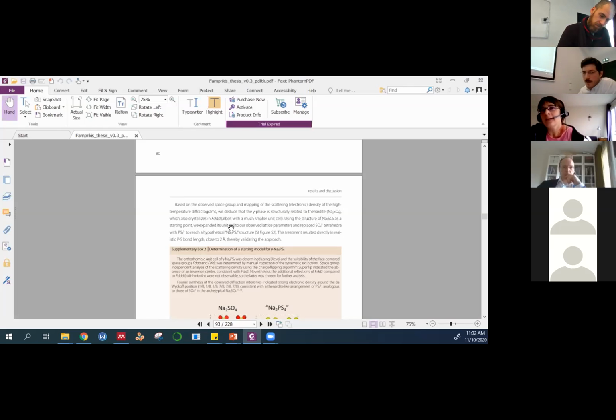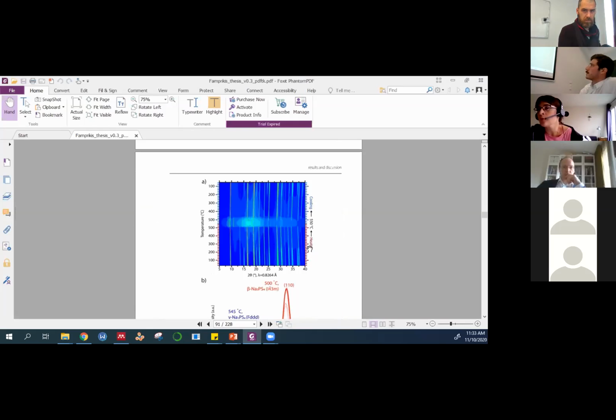Okay, but still, I'm not sure I agree fully with you, because you clearly have Bragg peaks, and they should be understood with a crystallographic model. This is my thing. Is there a possibility, for example, that at high temperature you have a slight change in the sodium content through the formation of an amorphous phase, and your crystalline phase has a slightly different stoichiometry that would explain why the symmetry is completely different? And when you cool back, it would reform the Na3PS4. You see what I mean? How can you be sure that in the gamma phase you have exactly this Na3PS4 stoichiometry and not something slightly different, in case you have some secondary phase forming, which would not be crystalline?